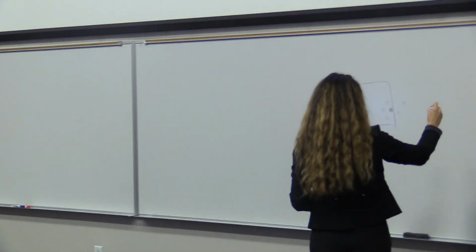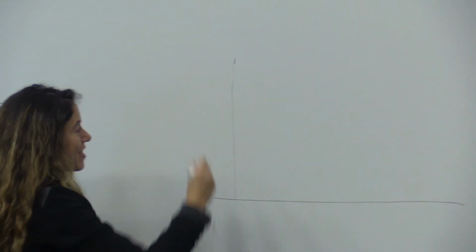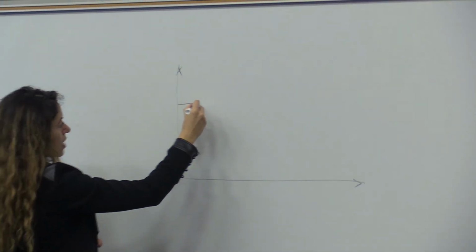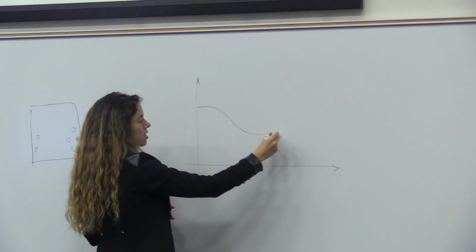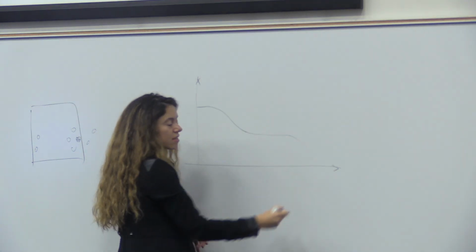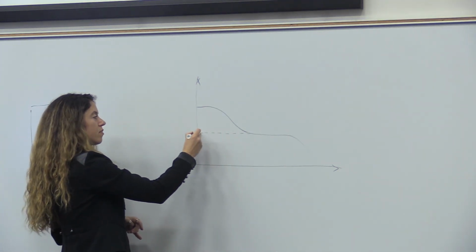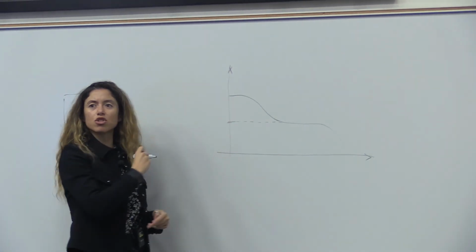Yes, so I think that you're referring to the Plateau Modulus. So the relaxation, if you apply a stress and it relaxes, so sorry, I might not say that very right, but the stress somehow decays as you let it relax, but it reaches a plateau because it is entangled. It needs some time to find its way until it drops. And this quantity where it stops for a while is called the Plateau Modulus.